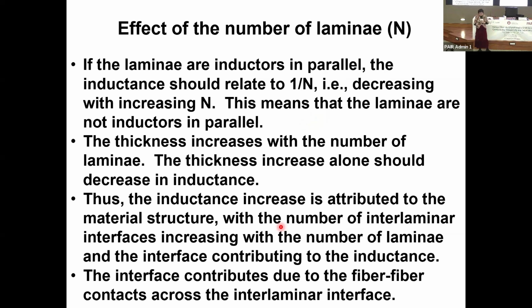The thickness increases with the number of laminae, obviously, and the thickness alone should decrease the inductance. Okay, but again, what you observe is the opposite. Thus, the inductance increase is attributed to the material structure, with the number of interlaminar interfaces increasing with the number of laminae, and the interface contributing to the inductance.